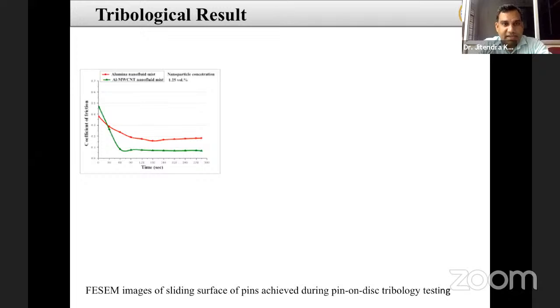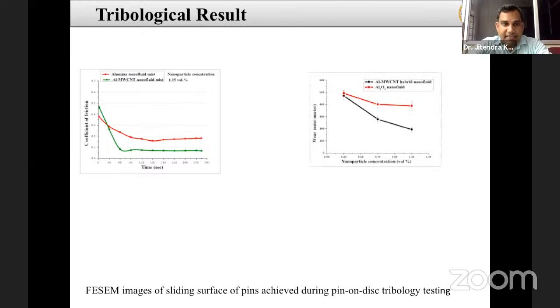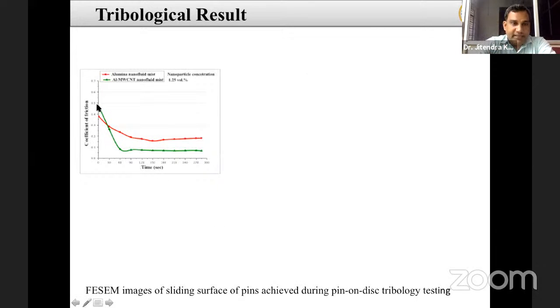So further, we also performed the tribological test on the same pin-on-disk machine, and these are the results with the cutting forces, coefficient of friction with respect to time. We found that initially the hybrid nano cutting fluid gives the higher friction, but after some time it gives the lowest friction. This is higher initially because more particles come into the contact, and after that they act to increase the lubricity, and they start decreasing the coefficient of friction because of that reason. Here only single nanoparticles, so because of that it starts low, and it also continuously decreases, but more decrement is observed in the case of the hybrid nano cutting fluid.